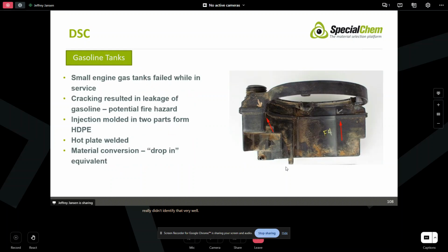Here we had some failures in some small engine gas tanks while in service. They were cracked, which resulted in leakage of the gasoline, which is a hazard. The two halves, the upper and lower, are hot plate welded. And there was a material conversion, which was touted as a drop-in. One of the high-density polyethylene resins was discontinued. And so it was said, well, we have this drop-in resin that works.